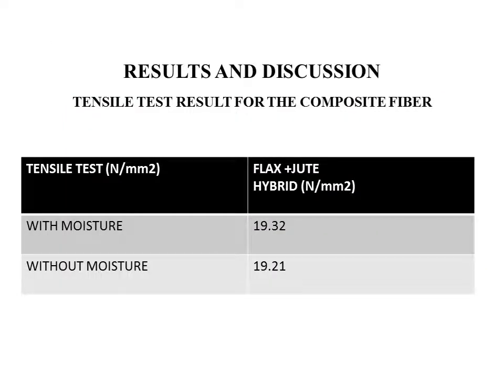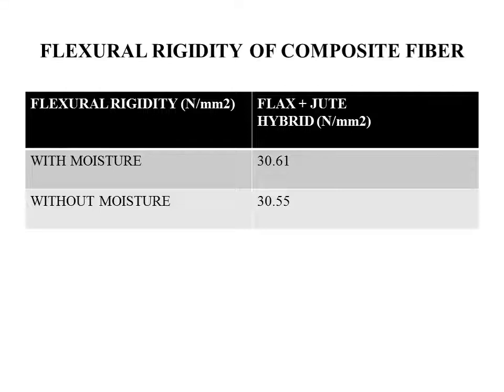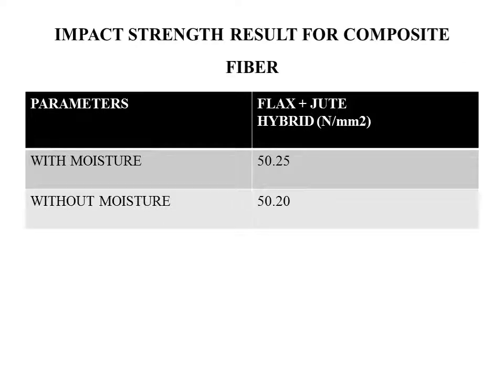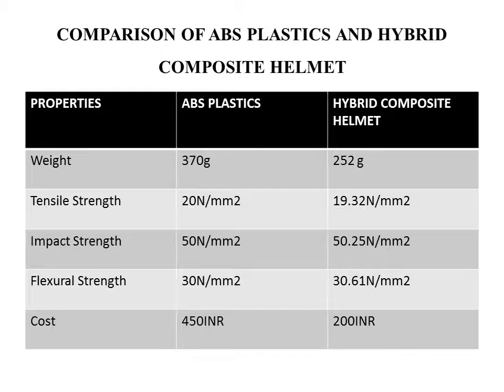Result and discussion. Tensile test result for the composite fiber: flax plus jute hybrid with moisture 19.32 and without moisture 19.21. Flexural rigidity of composite fiber with moisture 30.61 Newton per mm squared and without moisture 30.55 Newton per mm squared. Impact strength result for composite materials: with moisture 50.25 Newton per mm squared, without moisture 50.20 Newton per mm squared.